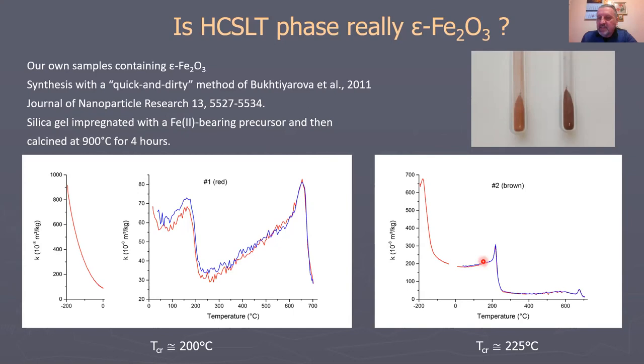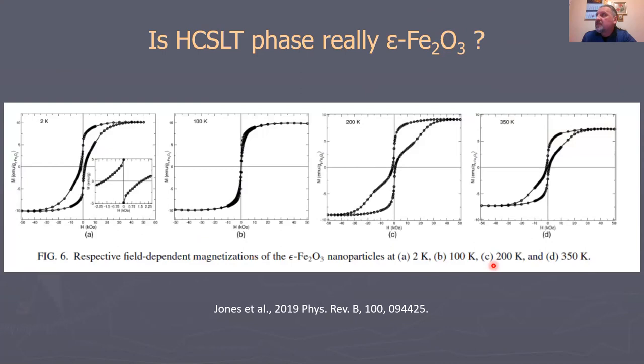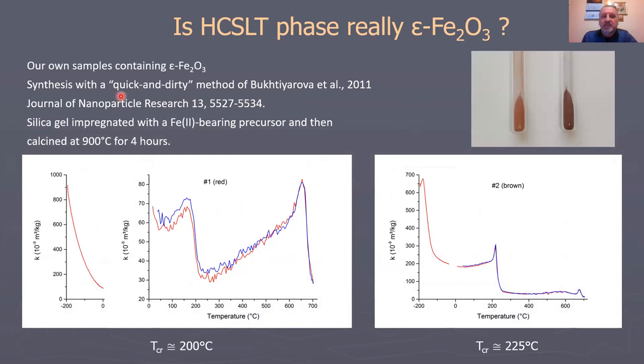So all these previous measurements have been done on highly perfect material using the approaches that are common in magnetic material science, and so we decided we could perhaps produce less perfect material that would resemble the archaeomagnetic sample a bit more. We did that using the quick and dirty method, where two different silica gels were impregnated with an iron-bearing precursor, and then calcined at 900 degrees centigrade for 4 hours.